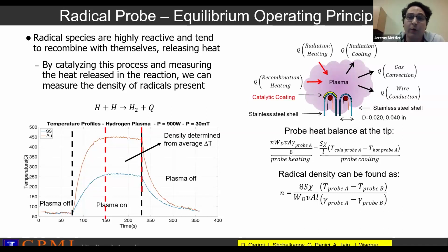And so the way a radical probe works is you typically take one or two thermocouples that can measure temperature, and you coat one of them with a catalytic coating, as you can see there with a little gold coating on the right. You expose both of these to a plasma, and if you've picked a catalyst that promotes the recombination of the radical you're interested in, so let's say hydrogen recombining to form H2, that's an exothermic process, and so it releases some energy. And if you have a much higher rate of recombination on one of your two thermocouples, you'll get a larger temperature response. And so you can measure that temperature difference, like you see on the curve down there in the bottom left. You can compare that temperature difference with the rate of recombination that you know for your gold and your stainless steel surface. And you can do some math, and you can back out that the radical density should in fact be proportional to that temperature difference that you've measured.